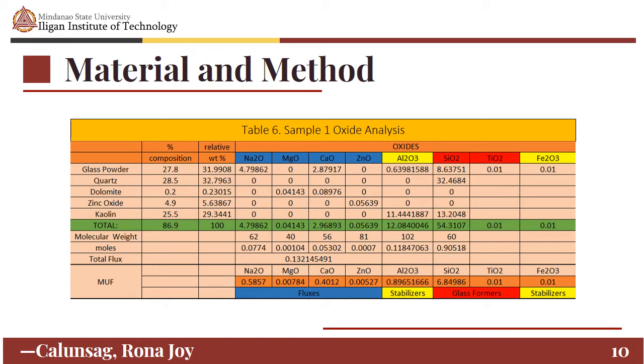For sample 1, the total fluxes have Na2O equivalent to 0.5857, MgO at 0.00784, CaO at 0.4012, and ZnO at 0.00527. For the stabilizers, Al2O3 has 0.89651666 and Fe2O3 has 0.01. For the glass formers, SiO2 has 6.84986 and TiO2 has 0.01.